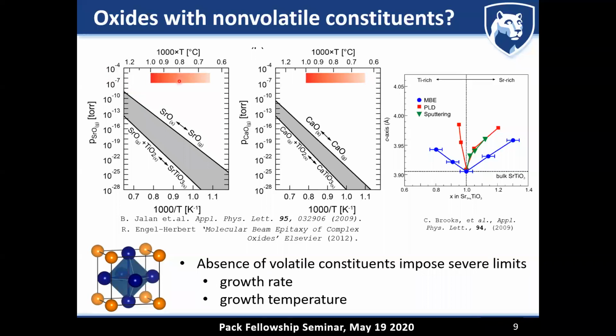Or the other thing that I can do is I can go to much smaller strontium oxide fluxes, which means, and you can see here that this is scaling in orders of magnitude, if I would reduce my growth rate by, let's say, 8 to 9 orders of magnitude, I would re-engage in the self-regulated growth window here shown in gray, and I would have access to a self-regulated growth. Now, both of these are really not a viable strategy to grow these particular complex oxides by molecular beam epitaxy.